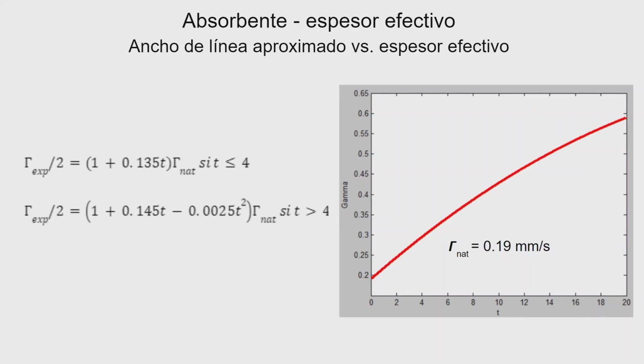And there are some expressions that are used to estimate the line width that you expect to have in your spectrum, depending on the size of your effective thickness, that can be used in different regions. So sometimes, as Jean-Marc said, you cannot have lines which are narrower than the natural width. I mean, but you will have certainly lines that are wider than this value. And the natural width, the full width at half maximum, is about 0.19 millimeters per second for iron 57.